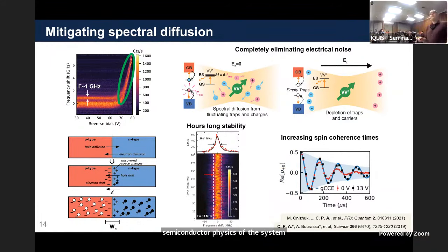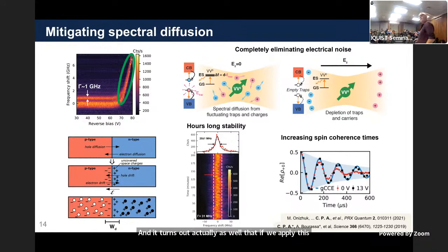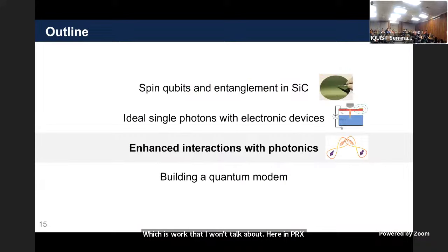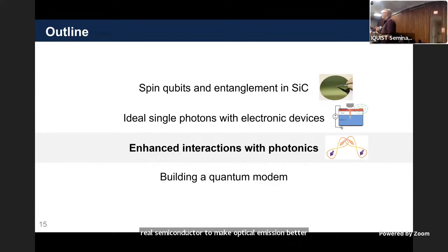And it turns out as well that if we apply this voltage in the system, we can also increase the spin coherence times, which is work that I won't talk about here, in PRX Quantum. So we can use our ability to engineer this real semiconductor to make optical emission better and spin coherence better. And we can only do that because this is a real semiconductor that you can dope and you can actually control the charges in it. So that's one of the key advantages of silicon carbide.